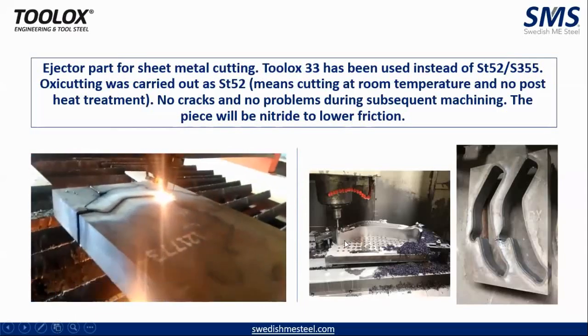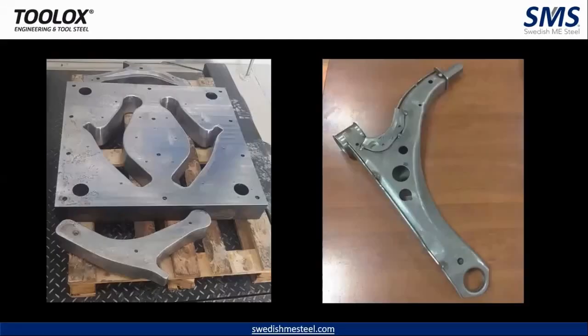So if this is the insert that you want to produce, you can directly cut your insert profile in the plate and machine only 5 to 6 mm of the heat affected zone. Compared to your regular manufacturing technique, this would save you a lot of time in manufacturing. Even after thermal input, there are no cracks, no problems in subsequent machining. So this is the component which has been produced.